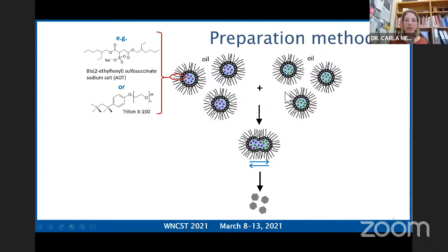We then mix those microemulsions together, and the reverse micelles will collide and coalesce and exchange their contents. We allow them to react for a particular time. And then we can induce a phase separation, for instance, by introducing an excess of the polar solvent, which can rupture those reverse micelles, induce that phase separation, and then we can collect the nanocrystals.